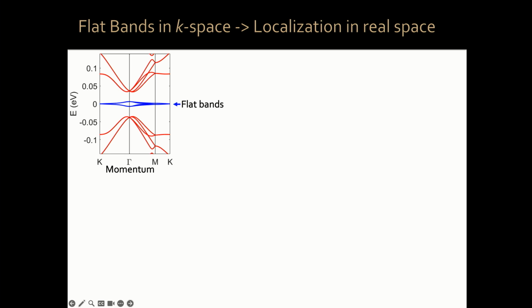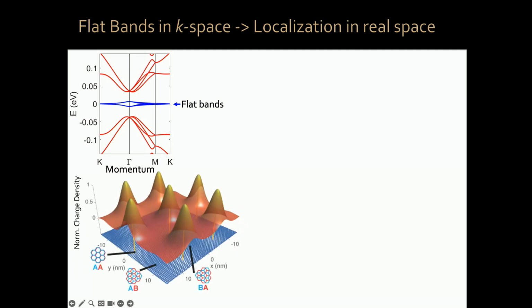Now, flat in momentum space, if you want to go back to real space and see where those electrons are, to go between momentum space and real space you have to do a Fourier transform. And the Fourier transform of an extended object is a highly peaked object. And that means that when electrons are in these flat bands, they like to be in certain regions of your Moiré pattern, which we call AA stacking, which means locally it looks like all of the carbon atoms are on top of each other in this twisted structure. If you move a little bit away, you go into regions of AB stacking because, with the small twist angle, the registry shifts and changes.